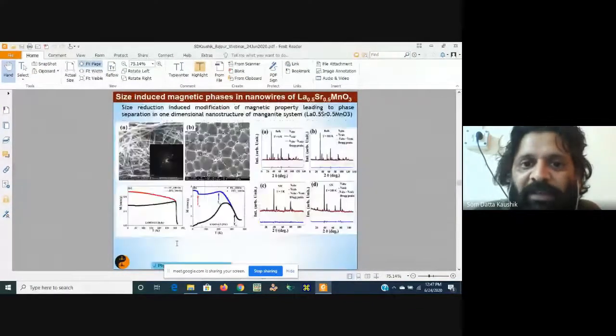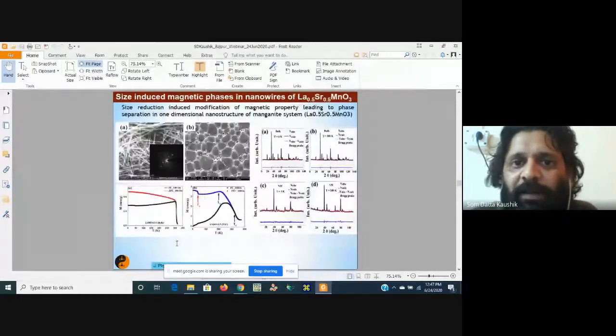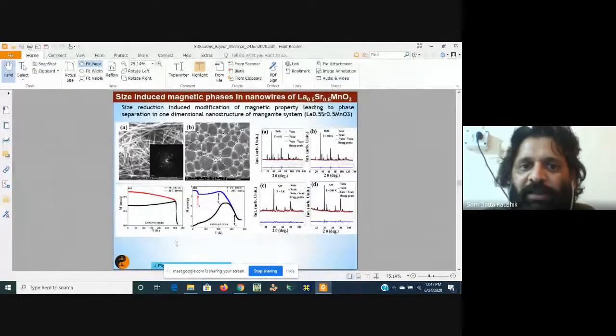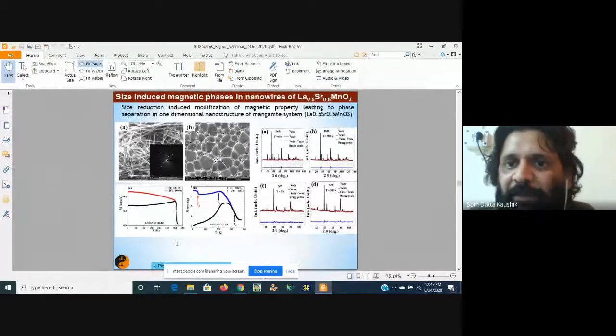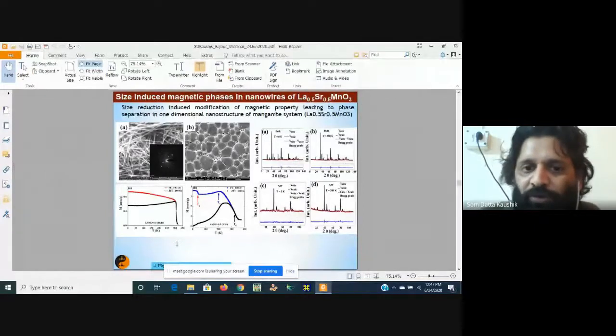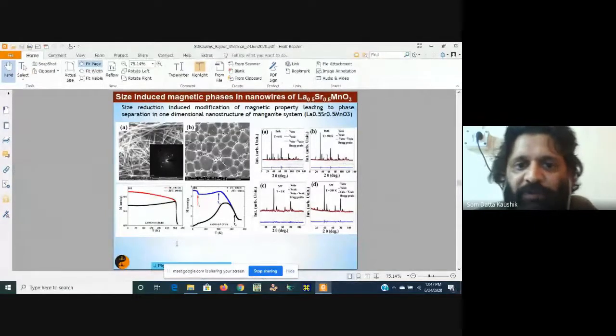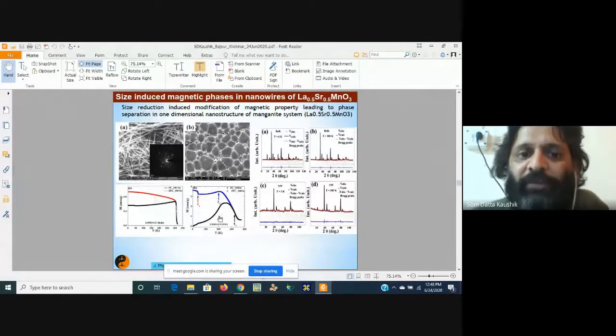One more thing is that using neutron diffraction, you can identify if you have phase coexistence or not. This particular compound is LaSrMnO3 in nanowire form. Upon low temperature neutron diffraction and low temperature magnetization, for the nanowire and the bulk there was a definite difference between the magnetization, but we could not identify what could be the reason for that.